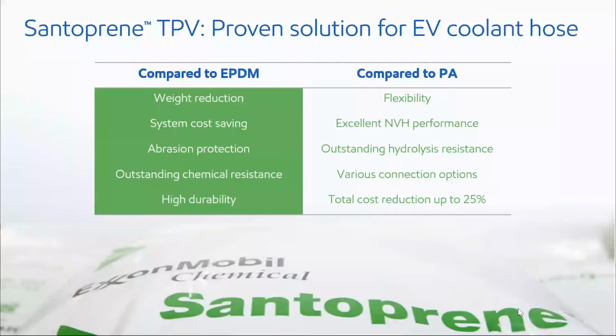Santoprene TPV has excellent abrasion resistance, and it also has very good chemical resistance and electrochemical resistance, which is very important for EV coolant hoses. So Santoprene TPV also offers long-term performance, like long-term durability. One of the issues with EPDM rubber or EPDM hoses is that after a period of usage in the service temperatures, the chemicals or the materials used in the compounding start to bloom or come out of the surface on the part, and this leads to hardening of the EPDM part, and it leads to cracking. This is very common in the EPDM industry, and this does not happen with Santoprene TPV. This is one of the major advantages of TPV over EPDM rubber.